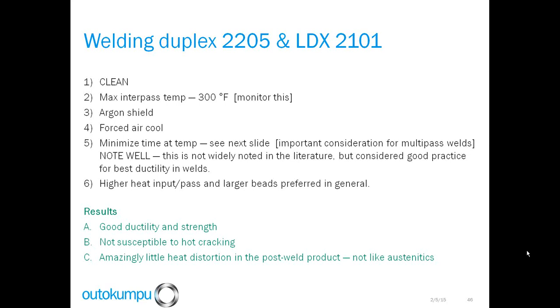So our welding practice with both of these alloys involves heat sticks. It involves somebody with a clipboard actually monitoring the welding. Argon shield, we had on this project did not use nitrogen as an adder. I might in the future, having learned that from Gary today. Forced air cool, a lot of air, try to get it through the critical zone fairly rapidly. And as I said earlier, I'll show you in the next slide, we did work to minimize the time at temperature and get down to the interpass temperature.